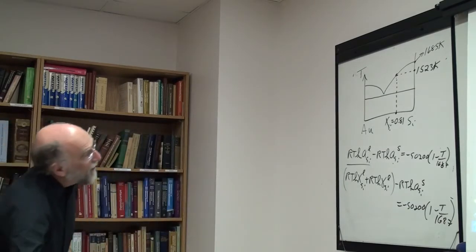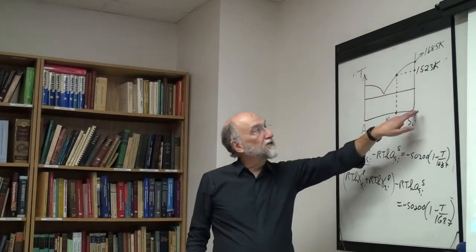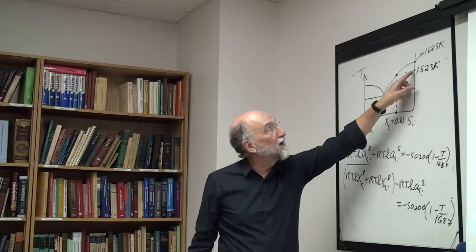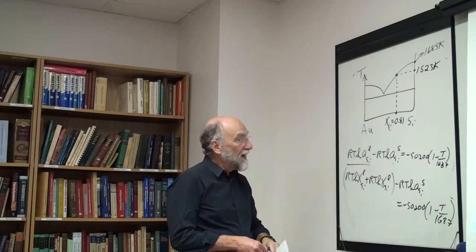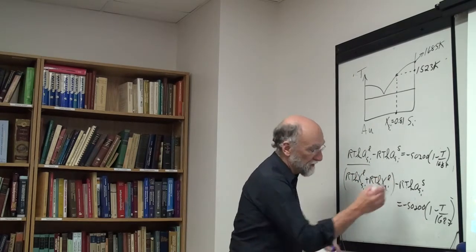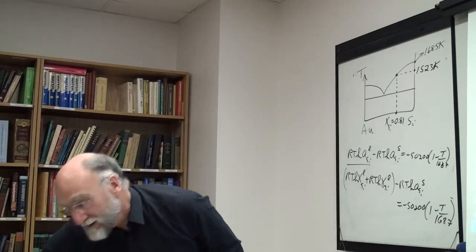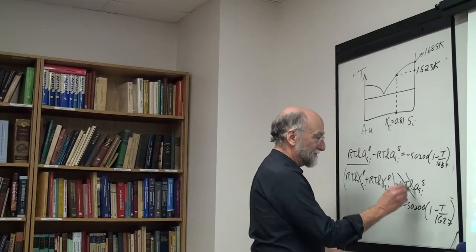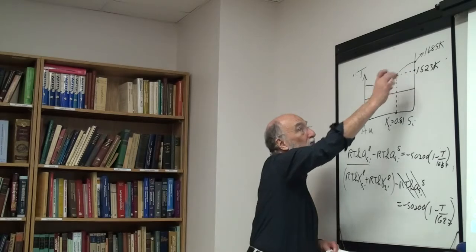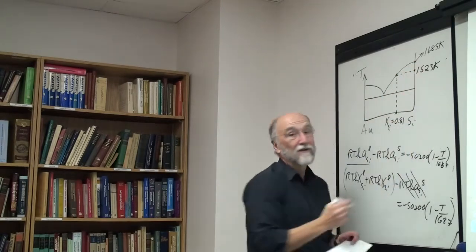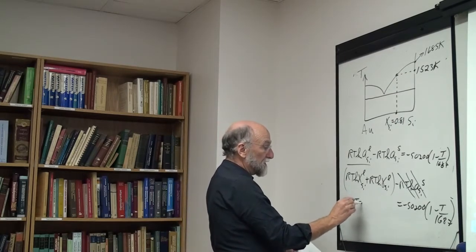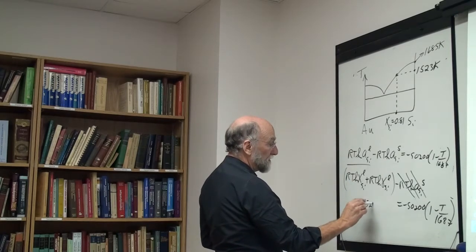Okay. Now from the phase diagram, we see that the silicon solid is almost pure. The phase diagram shows negligible solid solubility. In that case, the activity of silicon in the solid phase is equal to 1, so this term drops out. The activity of silicon in the solid equals 1 because the liquid is in equilibrium; the solidus comes down here vertically. Everybody happy?